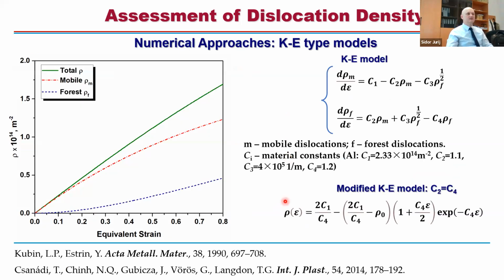levels. And apart from this, we wanted to know whether it's possible to catch it numerically. So in fact, the total dislocation density can be modeled by the original Kubin-Estrin model or a modified version of this model, which is actually an analytical solution. So in this Kubin-Estrin model, you have mobile dislocations and forest dislocations and constants. Those constants were already defined for various materials. For pure aluminum, I put them here.